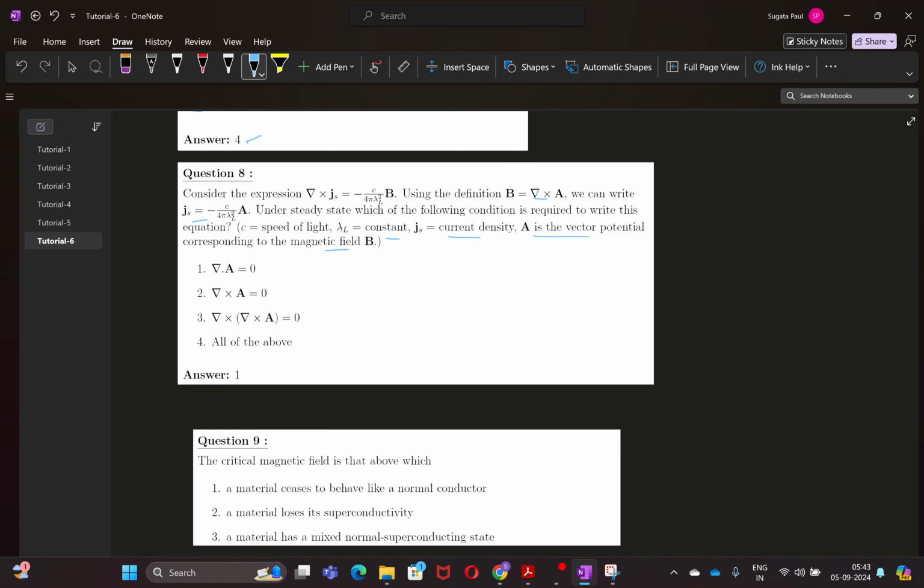Okay, so as I said, in the superconducting state the electrodynamics is different. To express those electrodynamics, the equation that is mostly used is called London's equation. These equations are extracts from the London equation that is valid for superconductors only. It is defined as curl of J equal to minus c by 4 pi lambda L square B vector. Note that lambda L is an effective length scale, an effective constant for this case.